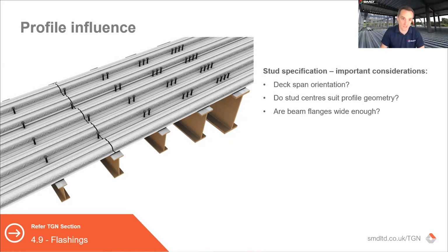That is the recommendation. As you then go up with different stud arrangements, 2 studs or more, the minimum beam width obviously widens, because the minimum space between 2 studs we saw earlier was 76. If you add the 2 30s onto that, that gives you a minimum of 136. So your beams need to be wider. So it's important to understand how wide the beams need to be to facilitate the stud numbers that you need for your composite beam.